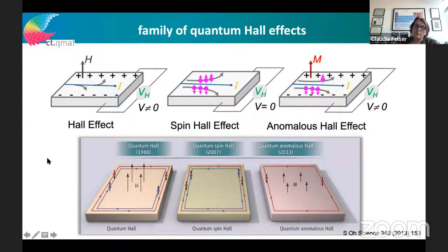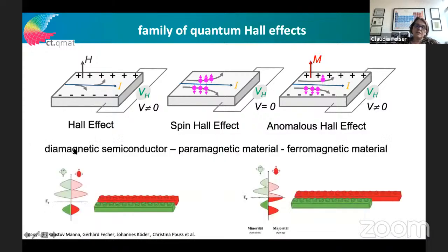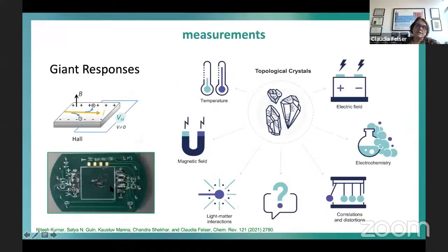To Hall measurements - this is what we like to do nowadays. So we like to measure our crystals by Hall. This is a setup: we put the crystals, which you have seen before, or maybe also the thin films, we make contacts, and then we measure the electric current in a magnetic field.